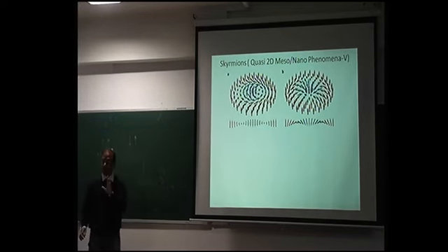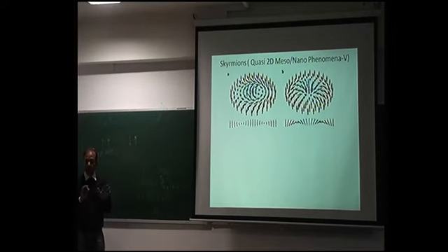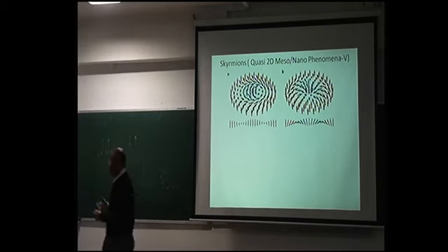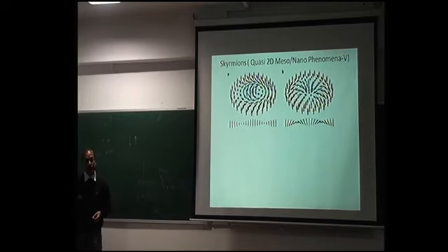So there is a deeper connection between the spin Hall effect and these skyrmions, because skyrmions in metal thin films can be observed where you have a strong spin-orbit interaction. For example, metals like platinum and tantalum are ideal materials for observing skyrmions in metallic systems.